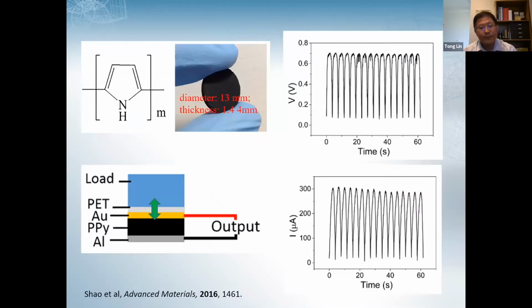This is our improved experiment. We prepared a polypyrrole dense disc by compressing the powder together. It is a round disc sandwiched between two metals, one aluminum, the other gold. On compression, you can see the device indeed generates DC power. Each peak consists of a compression and decompression action, and the many peaks come from many cycles. The output is about 0.7 volt for a disc around 13 millimeters in diameter and 1.44 millimeters thick. So this conducting polymer device can generate voltage output. The current output is about 300 microamps.